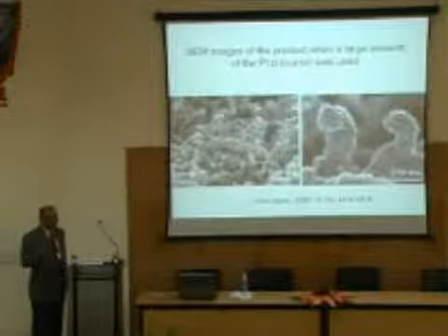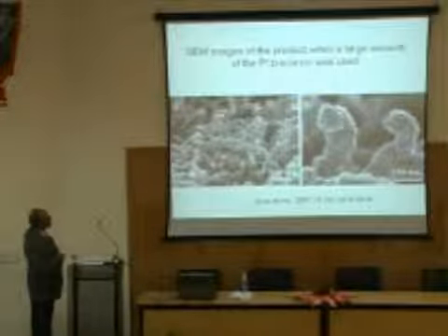If you increase the concentration of your solution, there are many controls. You can modify how much chloroplatinic acid you are taking, etc., by which you can generate slightly different kinds of features on the carbon nanotube. So here, these features you get when you use a much larger concentration of chloroplatinic acid.